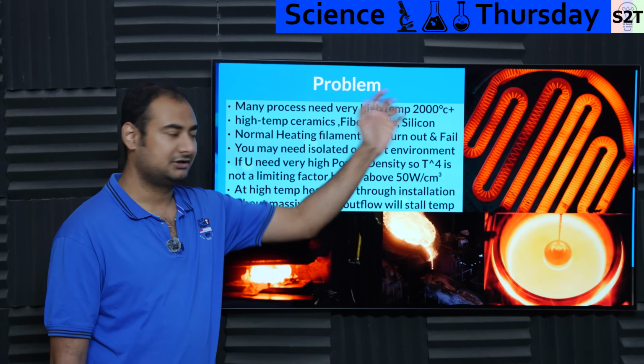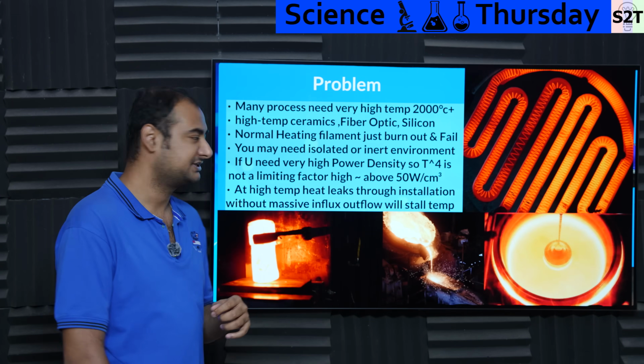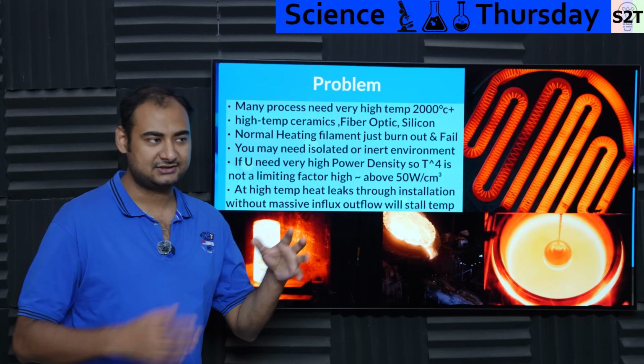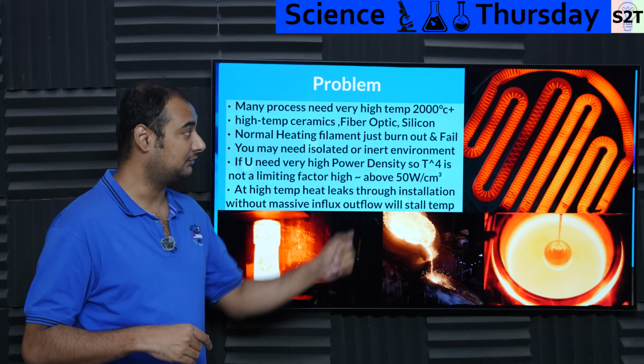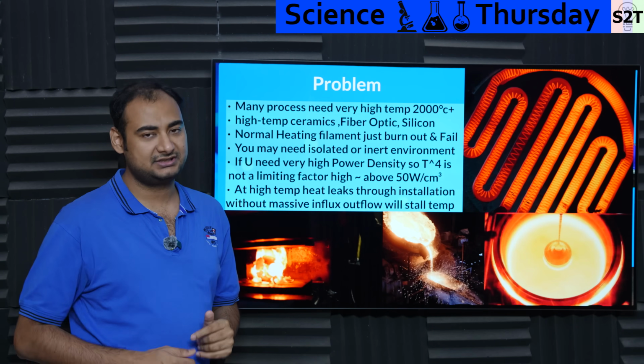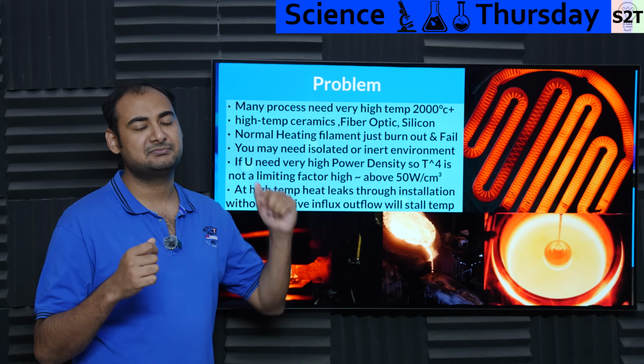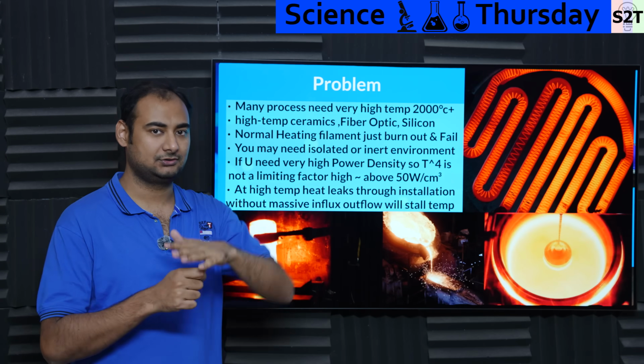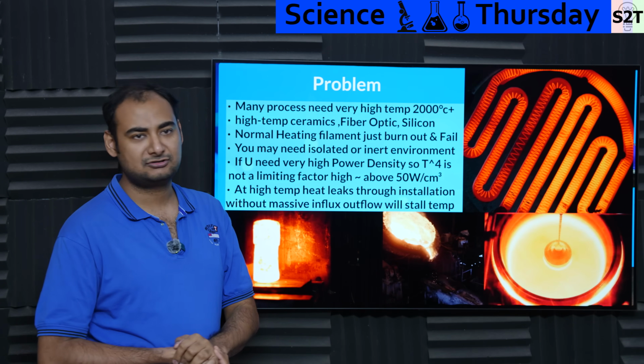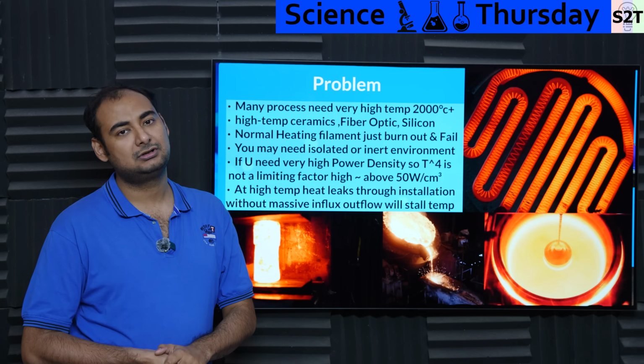And you're like, okay, can't we just use heating elements, high power heating elements? Well, here's a problem. There has to be a temperature gradient for heat to flow. For example, if your target is 2000 degrees Celsius, your heating element must be above that, only then will the heat flow. If that flow rate is not matched, either A, it will take too long, or B, it will